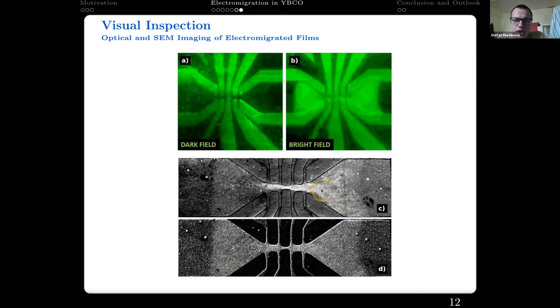If you look under an optical microscope, you see a change in reflectivity, as has been shown in some literature references that are commonly mentioned. But in the dark field optical imaging, which is also supposed to be a more topological contrast, we do not see any difference, indicating that there is no topological change, but that the change is truly in the stoichiometry of the material. But with the SEM images, we probably could say that it is filamentary and inhomogeneous.